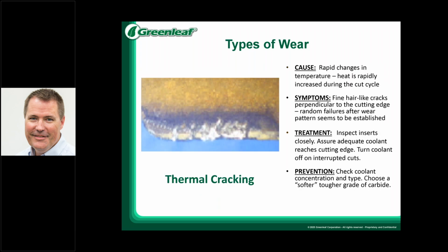Thermal cracking. These type of cracks are perpendicular along the cutting edge. It's caused many times in interrupted cuts. You'll see a dramatic change in the heat that's transferred into your carbide inserts in an interrupted cut through that heat cycling of going in and out of the material. If there's changes in the cut where it's being rapidly cooled along that edge, that's where you're going to end up seeing this type of thermal cracking.